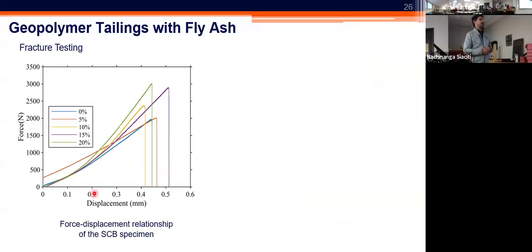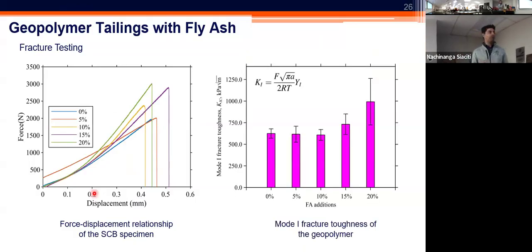In that case, we noticed that with increasing amounts of fly ash, the force or fracturing levels were increasing. If we apply the fracture mechanics concept and get the mode 1 fracture toughness for the material, we did notice that with the increase in fly ash content, we naturally had an improvement in the fracture toughness values. We compared these values with the fracture toughness of concrete and realized that they were pretty similar and within the same range as normal concrete. So we not only met the compressive strength of concrete, but also achieved a similar level of fracture toughness in our geopolymer bricks.